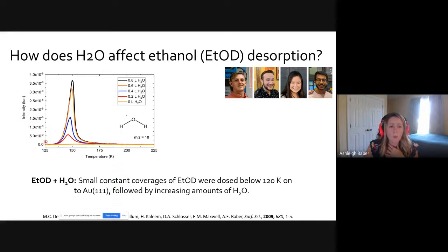So we can see in this plot here, we're just looking at a gold surface having a constant amount of deuterated ethanol on that surface and then slowly increasing more and more water that's co-adsorbed on that surface. And basically how we do it is we dose ethanol first, we add water on top of that. This is all happening around 100 Kelvin, and then we run the TPD and look for desorption products. Okay, so as we add more water, we see more water coming off of the surface. This is a really good start.